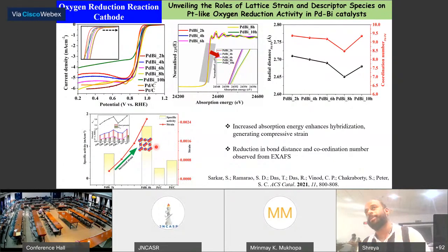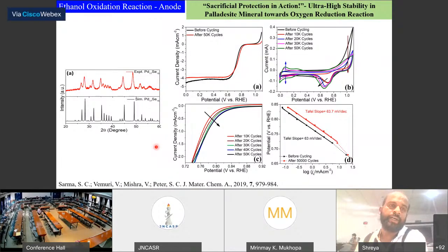This is well complemented by our theoretical studies, where we induce the strain within the system in the DFT calculation. Then we understood that strain plays the major role in enhancing the activity. If you go to the anode side, we have a classical example. We propose a sacrificial protection in action, where there is palladseite, a mineral that is only found in Brazil, Pd17Se15.